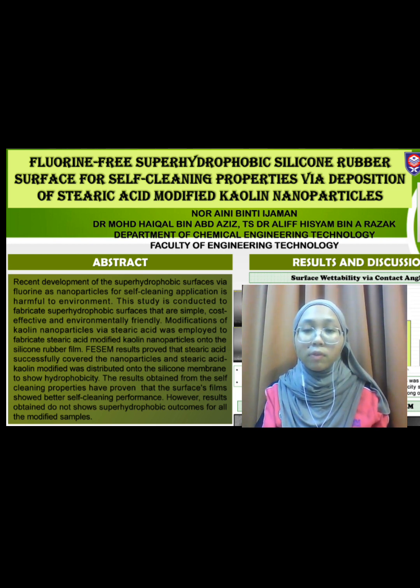surface. Results prove that stearic acid successfully covered the nanoparticles and the stearic acid modified kaolin was distributed onto the silicone membrane to show hydrophobicity. The results obtained from the self-cleaning properties have proven that the surface film showed better self-cleaning performance. However, the results obtained do not show superhydrophobic outcomes for all the modified samples.